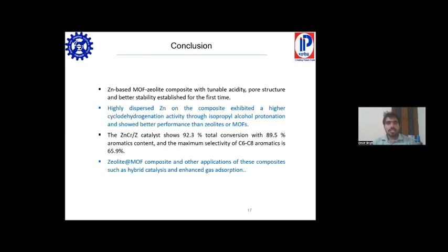Then come to conclusion. The zinc-based MOF composite with tunable acidity and pore structure gives better stability as compared to pure ZSM5 catalyst. The high dispersion of zinc in the composite gives cyclodehydrogenation activity of IPA to give aromatic hydrocarbon. As we found, the ZnCr/Z (zinc chromium on zeolite) catalyst gives a good performance, that is 92.3 conversion and 89.5 aromatic selectivity.